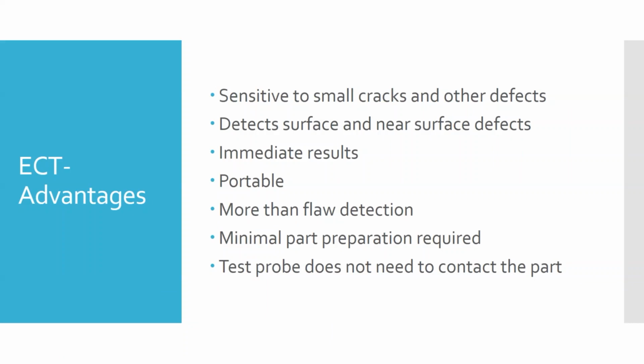And your test probe does not even need to contact the part. In some cases, this is done in a non-contact. Aviation, most of the time we're doing a contact type system. We're putting the probe directly up against the surface. However, if you think about it, it's technically a non-contact, as we're not actually contacting the surface we're testing, we're contacting the surface of paint. And there's actually a little gap between the face of the probe and the metal underneath, the thickness of the paint, where we're not really worried about what's going on with the paint. Paint cracks, you can see, not as critical.